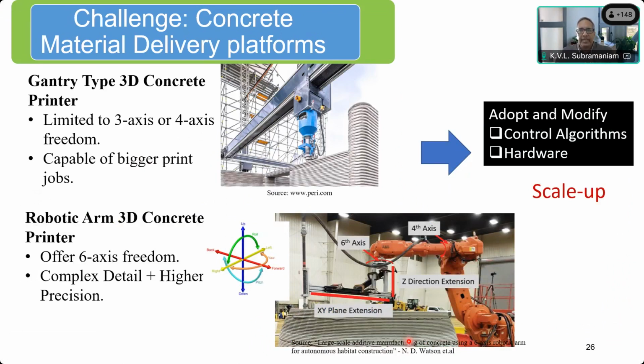So you're pumping concrete, but it has to be placed precisely, which means that I need some way of controlling the head. The head is basically wherever you have your nozzle. So you see this pipe, this is the pipe that is conveying the concrete. And please remember, this concrete, as we are talking today, if you look at it, looks more like paste. And it is because we are limited to smaller sized aggregate. And as this nozzle moves along, it starts depositing concrete.